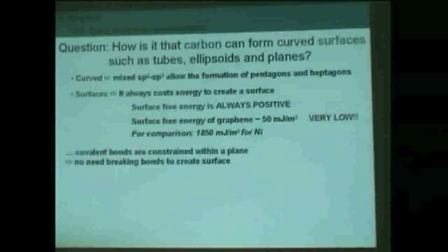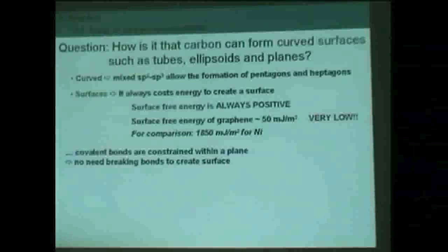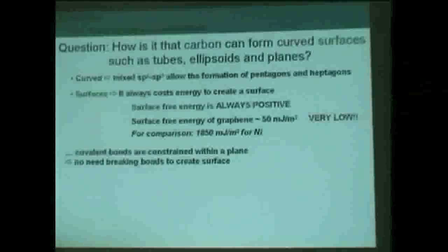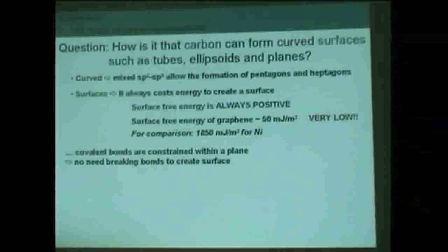Why is that? It's because when you have sp2 bonding, all the bonds are constrained in a plane already, so there is nearly no bonding out of the plane, or very weak bonds. It's very easy to break those bonds, just van der Waals bonding, so the energetic cost is very low. This is why it's so easy to create surfaces of graphene and derived materials like fullerenes and nanotubes.